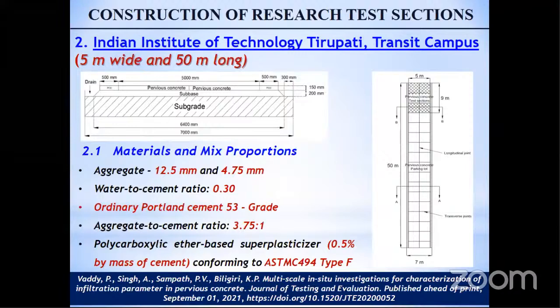The next study that I'm going to talk about was a test section which was constructed on campus at IIT Tirupati. This section was about 5 meters wide and 50 meters long. You can again see the materials as well as the mix proportion details presented on this slide. The aggregate size varied between 12.5 and 4.75 mm, and the water cement ratio here was slightly lower as compared to the previous work, where it was reported as 0.32. In this case, it was about 0.3. Again, OPC cement was used, and the aggregate to cement ratio was 3.75:1. The results of the study have already been published in one of the international journals with ASTM, the Journal of Testing and Evaluation, which can be referred to for further information.